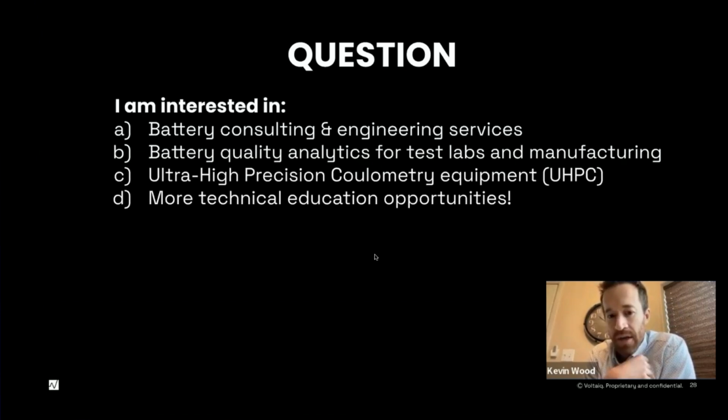and then monitor that, because you're looking at a DQ and a DV, but you also have to realize that you're going to have kind of a combination of potential effects there, since the current is not constant, the transport and the kinetics are going to vary. But by using the static DQDV method, you're going to reduce the effects of transport and kinetics. So hopefully your analysis would be a little bit less convoluted, if that makes sense. So that would probably be the way that I would initially try and answer that question.